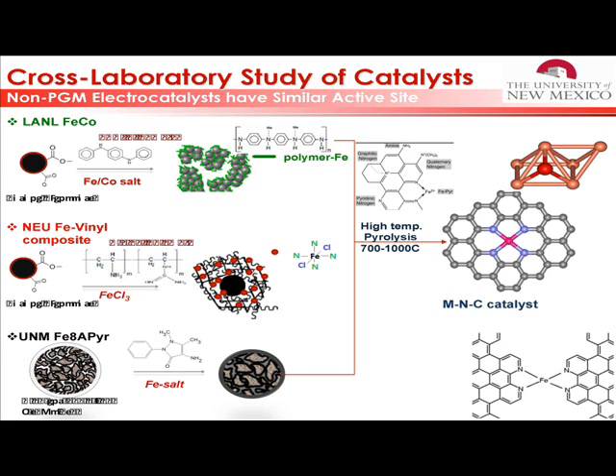And as a result, catalysts that are made so the majority of the active sites are here, but not here, will have a diminished behavior at low pressure. They will be very much pressure sensitive because if you can supply your water at a high pressure from here, you can push and open these pores. Not open, but access these pores.